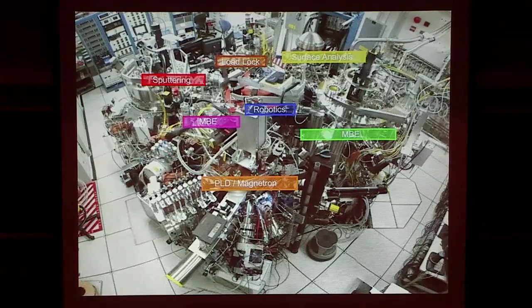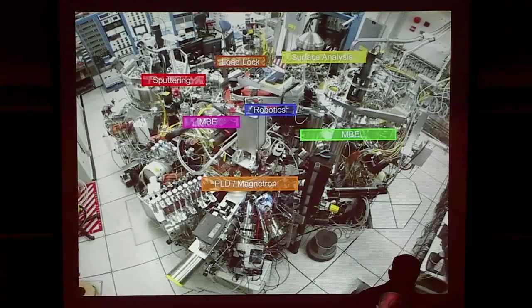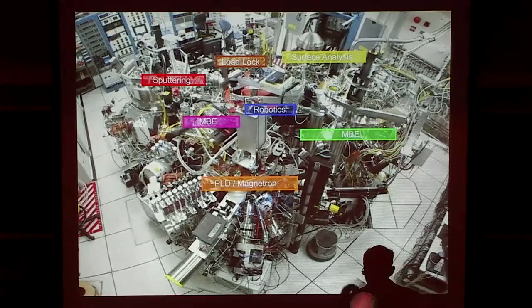And we can use different techniques for depositing these atomically thin layers. So we use techniques such as molecular beam epitaxy, something called PLD, pulsed laser deposition, and something called magnetron and ion beam sputtering. And in this system, we actually have about 80 different sources of materials. So we have an ability to explore a wide range of materials. That's all I want to say about this. What's remarkable, though, is we can actually, in the laboratory, see materials whose properties depend on these atomically thin layers. And we can actually take these and manufacture them on a mass scale.